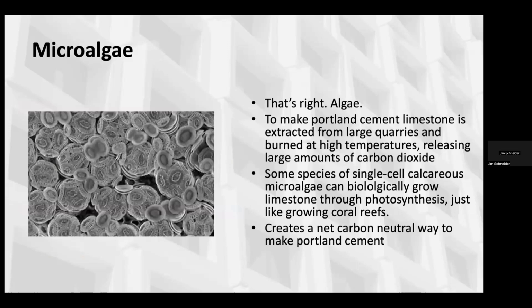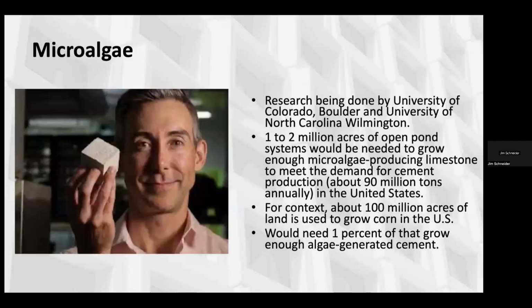So the idea here is to actually make cement limestone. Right now, we make cement limestone by extracting it from large quarries and burning it at high temperatures, and that creates all this carbon dioxide problem. So some species of single cell microalgae can biologically grow limestone through photosynthesis, much like growing coral reefs. So this would create a net carbon neutral way to make Portland cement. There's research being done up the road from me here at the University of Colorado Boulder and the University of North Carolina Wilmington. So there are some interesting possibilities here. One to 2 million acres of open pond systems would be needed if we were to really say, you know what, we're replacing traditional limestone for cement in the United States with microalgae generated limestone.